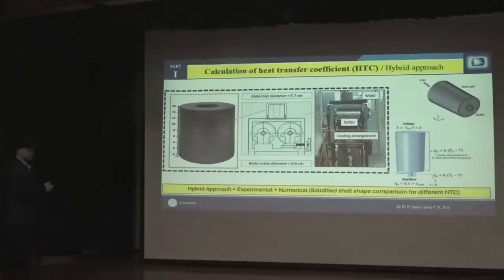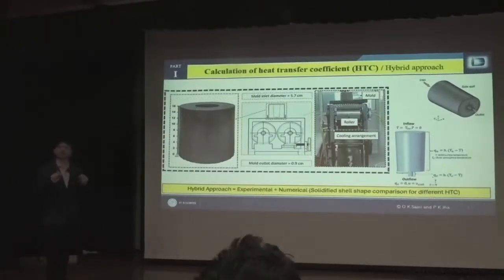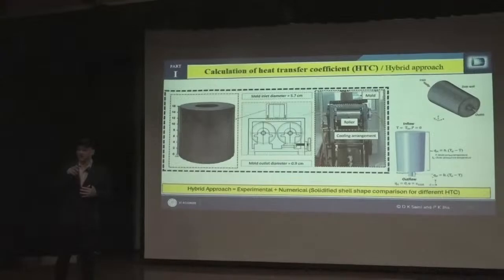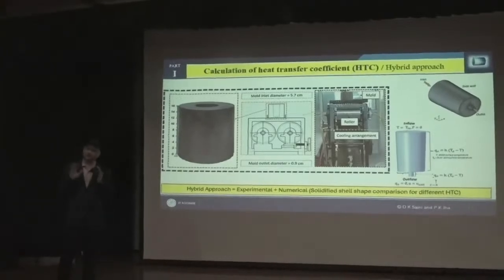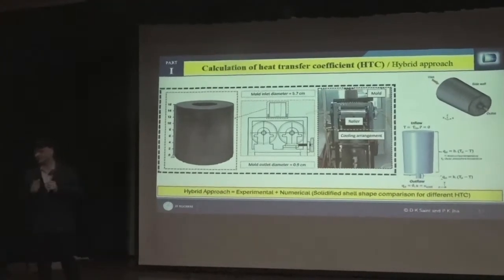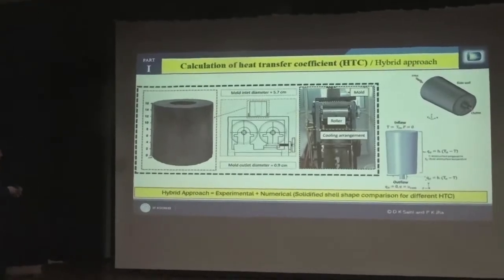Now this was done with a graphite mold, and in the graphite mold the metal was given. The thing is that when you start, finding the heat transfer coefficient is important. Normally you give one heat transfer coefficient and you try. Now most of the challenge is that if an improper heat transfer coefficient is taken, it will give you some result, but not realistically correct.